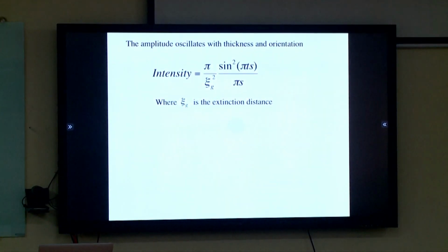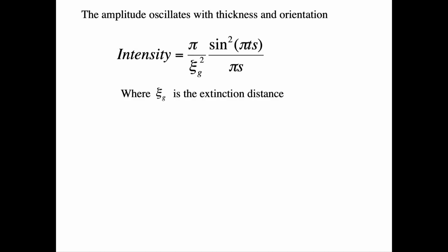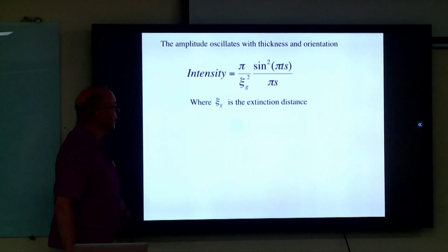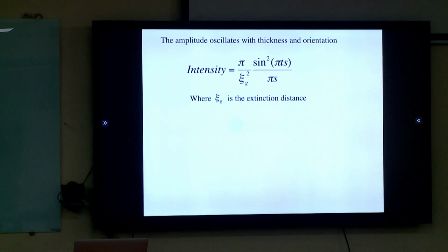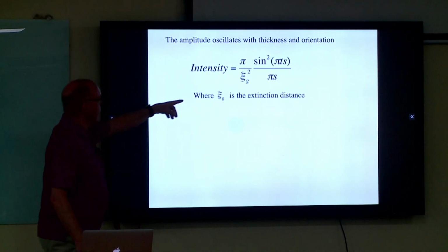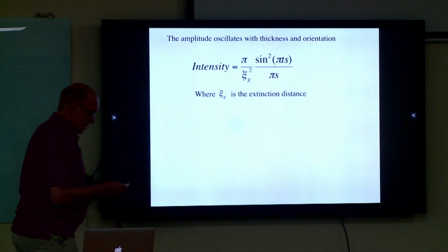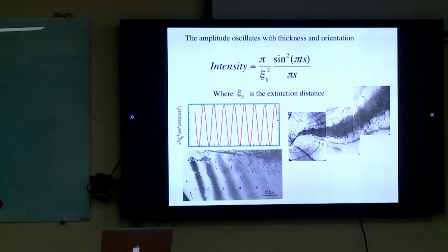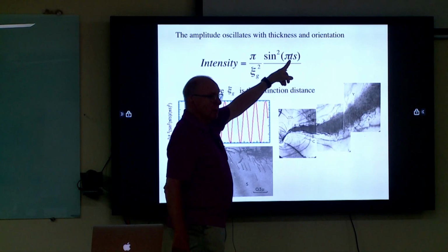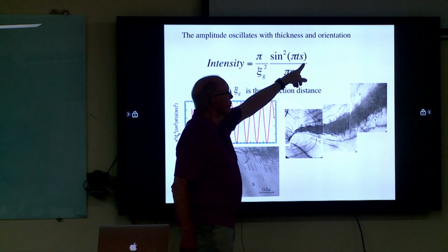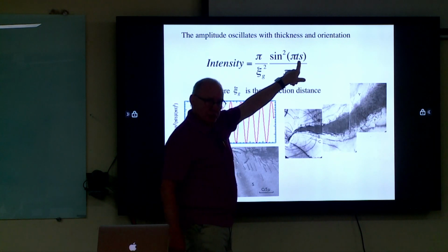And so we think, this is kind of looking like an important equation, so that's nice, a bit more complicated for us simple metallurgists. So we think we're on the right track. And this thing here is called the extinction distance. We'll get back to that. And interestingly, this says there should be a variation with the thickness and also with the deviation, with the orientation.